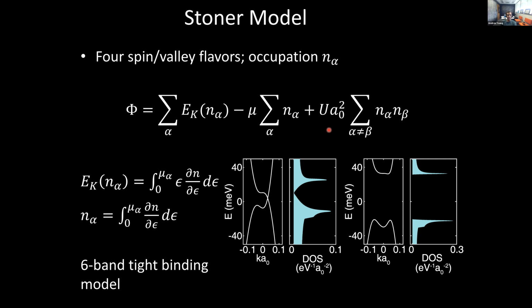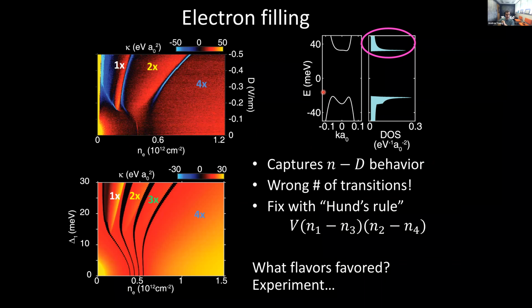It's pretty phenomenological, but it does account for the density of states through this E sub k, which is a calculation of the energy required to fill the single particle band structure. So this is going to build in some repulsion term, which favors occupying states of the same flavor. In this case, the alpha and beta range over different spin and valley flavors, and the single particle density of states. We can put that in for 0 displacement field, where the density of states looks like this, or for large displacement fields, where it looks like that, and so on. We can put in all the band structure details. It's of course notoriously difficult to calculate this Coulomb repulsion accurately, but we're just going to set it to be a number.